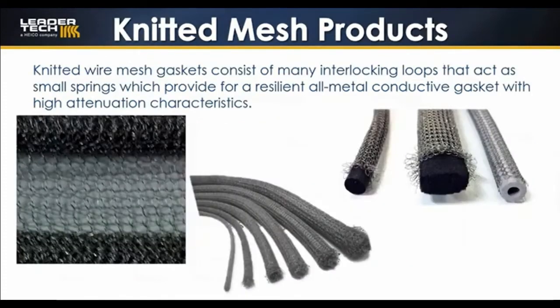Knitted wire mesh gaskets consist of many interlocking loops that act as small springs which provide for a resilient all-metal conductive gasket with high attenuation characteristics. It can provide shielding effectiveness up to 130 decibels in the E field and up to 80 decibels in the H field. The standard wire materials are tin-plated copper-clad steel, Monel, and aluminum in cross-sections of rectangular, round, round with